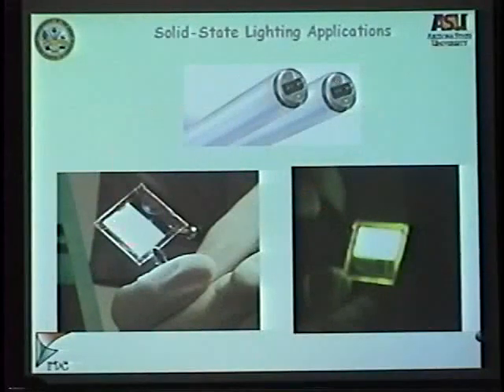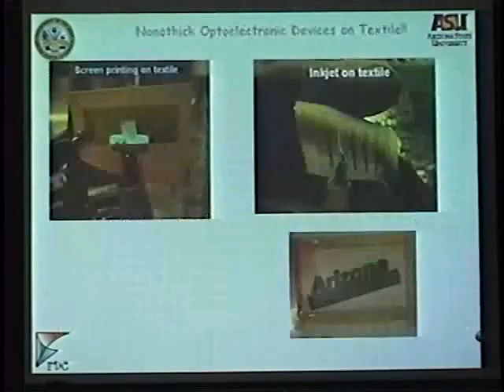This technique could be very useful in printing organic light emitting diodes that have a wide spectrum for solid state lighting, and this is about a 2-inch wide light, about a cell phone application basically, that was printed in our lab. It's a single layer organic white light material. We can adjust the color. You can go white, yellow, and any color very easily by doping these organic materials with a particular dye or talking to a chemist and having them change the structure a little bit.